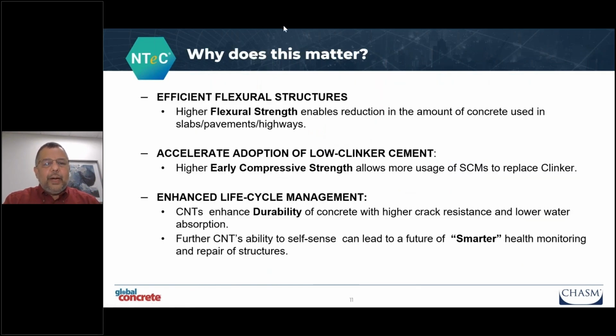So what does it mean? Why does this matter? What do we do with it? We took an approach very similar to our previous speaker's: how do we increase the efficiency of concrete? Higher flexural strength can mean thinner pavements or thinner slabs within the compliance of the codes with no change to the cement. Which means it's not all about reducing the clinker, it's about reducing the amount of concrete you use for a particular purpose and yet being code compliant.